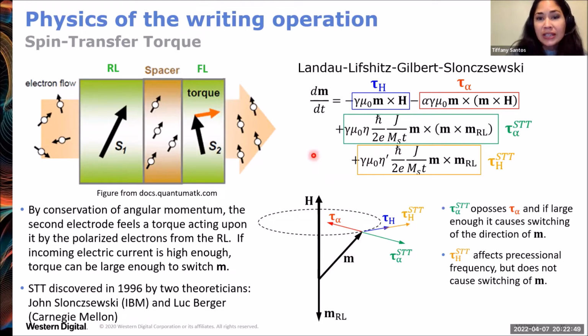So showing here the Landau-Lifshitz-Gilbert equation that describes the precessional motion of the moment around an effective field. The Slonczewski terms here, this green and orange terms, they are added when a current is passed. I just want to point out here that the spin transfer torque, the one that's acting to flip the magnetization, is directly opposed by the damping torque that wants to pull the magnetization back towards the field into equilibrium state. For this reason, for the free layer material, we want to minimize the damping parameter alpha as much as possible so that the spin transfer torque can be most efficient in flipping the magnetization. Okay, so spin transfer torque was discovered in 1996 by 2 theoreticians, John Slonczewski and Luc Berger.